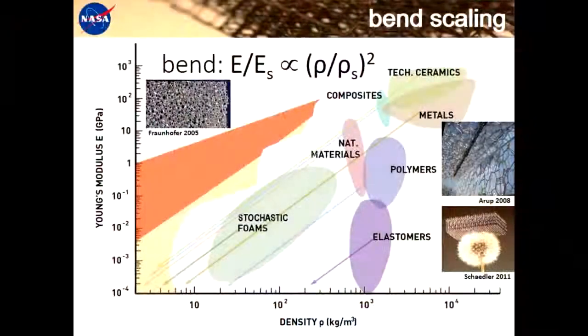So we're still left with the red area on this materials property graph, which is physically possible, but for which we still have yet to show suitable methods of fabrication. So we do have methods of creating cellular materials with greater reductions in mass density than the 1 to 10 that I just mentioned. So these, however, have the property that instead of material stretching, the phenomenon that governs their behavior under load is bending. This results in the bulk following reduced mechanical property laws, which is shown here.